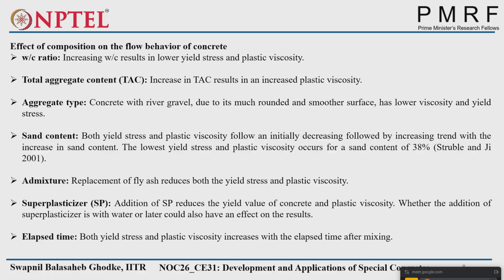Suppose now one more study is there in the rheological aspects. You have the concrete or cementitious material with the same rotating speed or shear rate. You are checking its yield stress. Suppose you are checking yield stress at 0 minutes after directly mixing the material, then 5 minutes, then 10 minutes, then 15 minutes, 20 minutes, 25 and 30. Similarly, at 5 minute gaps.